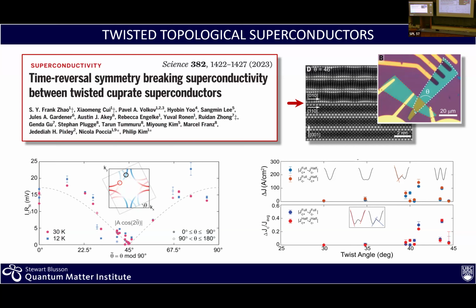However, things get very interesting in this region, where the leading term, the linear term, is going to zero. Now you can look at nonlinear terms. And as you look at nonlinear terms, again as a function of twist angle, you can start looking at what is called a superconducting diode effect. And really you have to be in a region where the linear term is going to zero, so away from zero, approaching 45. But also you cannot go to 45, otherwise the superconducting diode effect also will go to zero. So I want to attract your attention to the fact that you have no response here, no response there, but there is a region here in the middle where now you can see that the signal for what is a diode current, a diode effect, goes away from zero.